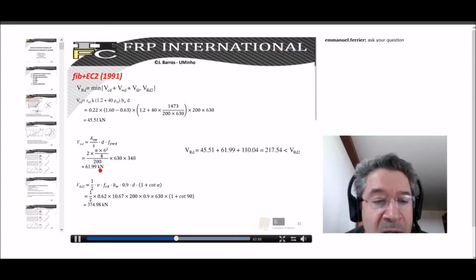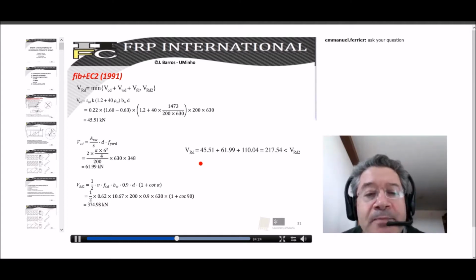And the term that evaluates the maximum value that a beam can support in order to avoid crushing of the concrete is obtained according to this equation. Finally, we obtain about 375. Consequently, we are able to estimate the load carrying capacity, or the shear capacity, of the beam. That is the addition of the contribution of the concrete plus the contribution of the steel, and finally the contribution of the FRP. And since the addition is lower than the term that corresponds to concrete crushing, this is the final value of the shear capacity of this beam, according to the FIB plus EC2.